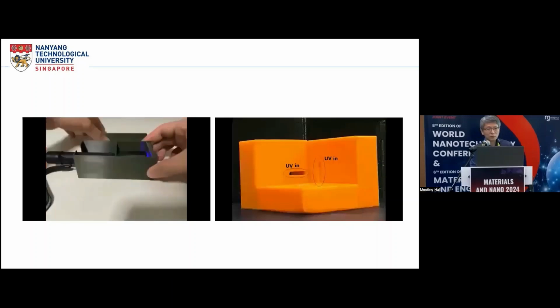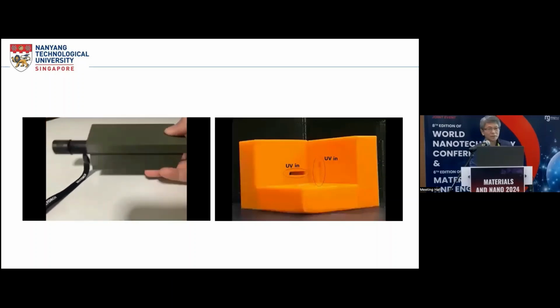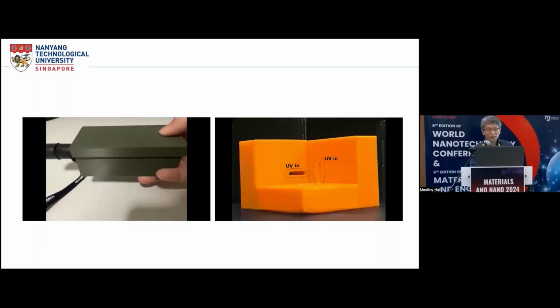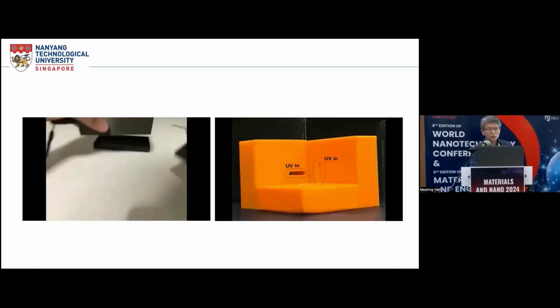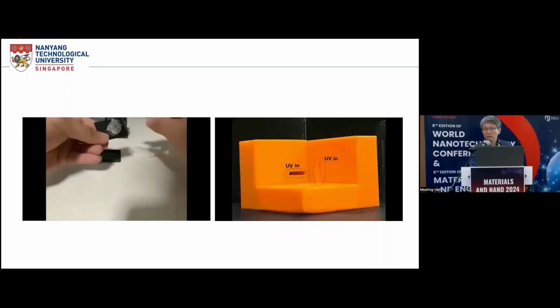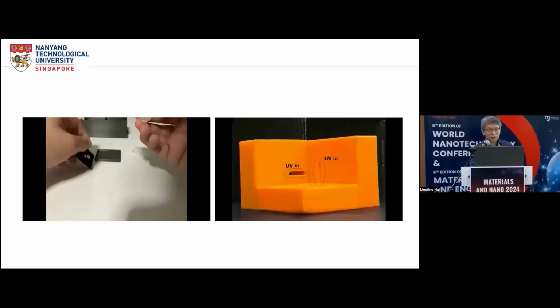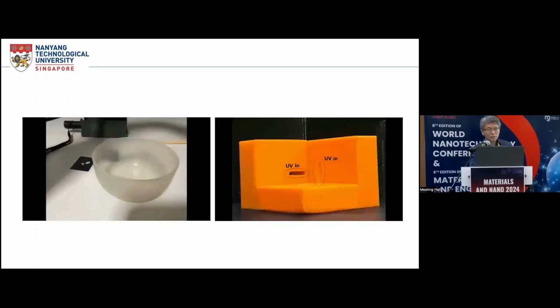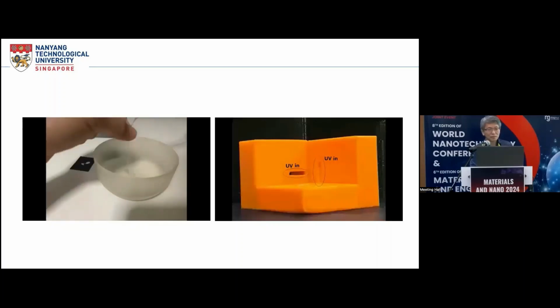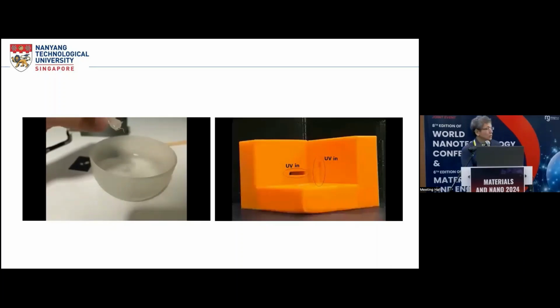And the remaining material, which is uncross-linked, we can reuse, as you can see. We do the same thing, shake again, and cross-link. And this time, we use boiling hot water to separate the cross-linked part from the uncross-linked part. Okay, we use hot water for separation. It appears that using your hand to separate is more effective than using hot water, because the uncross-linked part upon heating to high temperature is quite sticky.